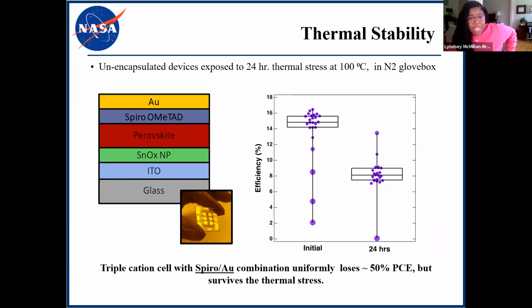So in the first case, we took this unencapsulated device with a Spiro hole transport layer. And on the right, I have pre-stress versus post-stress efficiency distributions. So we're surprised, but they survived the thermal stress. And we see about a 50% power conversion efficiency loss.